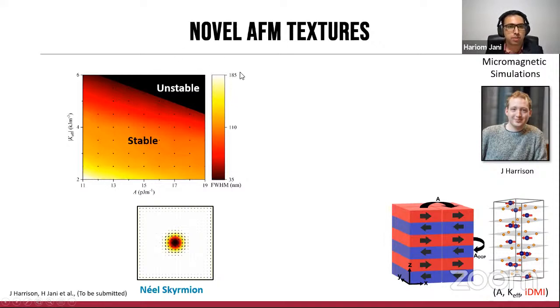And then if we go to the higher end of this regime, we are not able to stabilize them, in the sense that these skyrmions shrink and they vanish to zero. So as shown here, the sizes of these objects are much smaller as compared to bimerons, going all the way down to about 30 nanometers. This is, of course, limited by the micromagnetic approximation. So we expect that by appropriate scaling, this number can even go down further in the system.